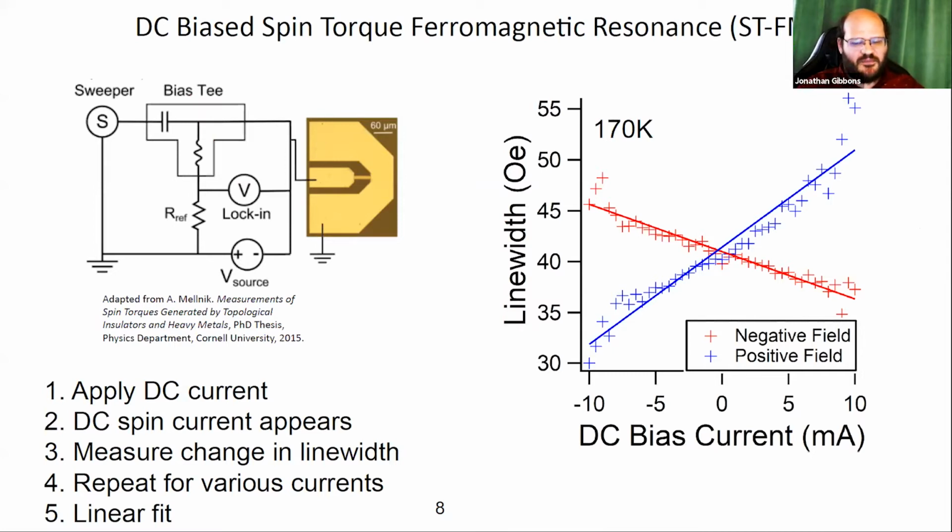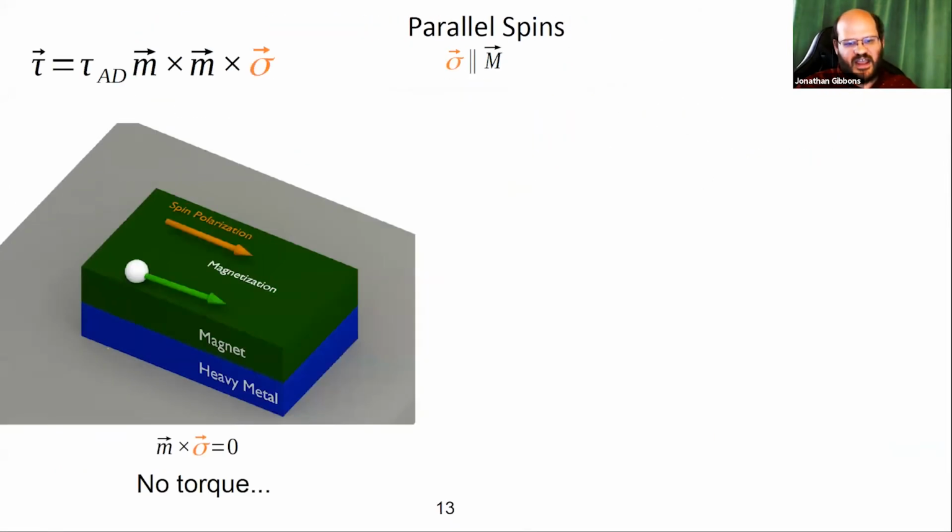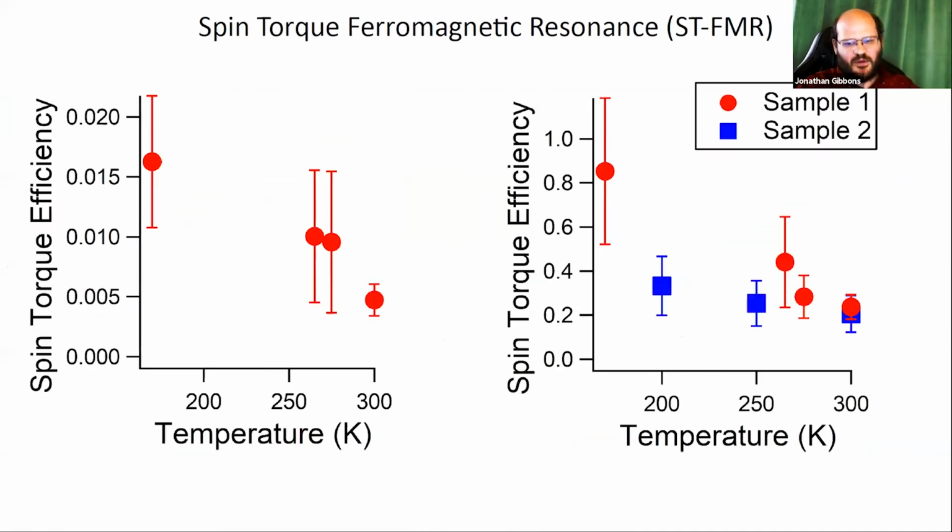There are some schools of thought on why this happens. It's thought that this could be a heating effect, but you see this fairly regularly in this measurement, that often the slopes are different. The way we've dealt with this is we averaged the two slope directions. And in fact, we have error estimates that include the difference in the two slopes. I can also bring up our results after error estimates, which are shown here.